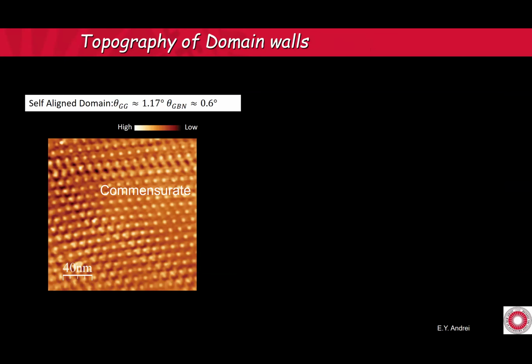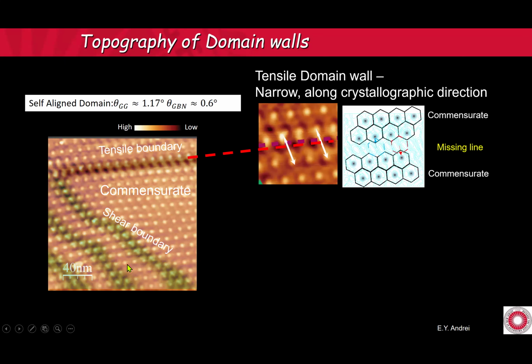Okay, so this is an example. Here we have a commensurate lattice. And just to make this clearer, you see that we have a tensile boundary here and we have a shear boundary here. It kind of zigzags. It likes to go along crystallographic axis. If you zoom in here, in the tensile boundary, you see that the moires are kind of stretched and you leave an empty spot in between. You have a missing line here in a sense.